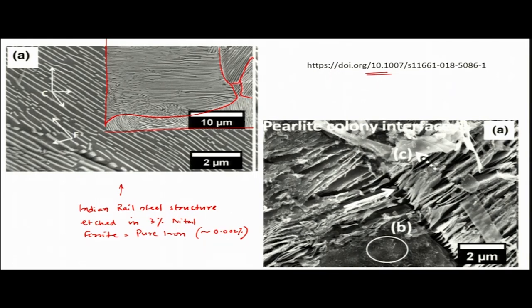At around 850–900°C the austenite grain forms, and when cooled down, pearlitic nucleation starts at the prior austenitic grain boundaries. Each grain shows a similar pearlite orientation — one set of orientations per grain. For example, one grain has one orientation and an adjacent grain has a different orientation, confirming these are prior austenitic grains within which pearlitic nucleation occurred.